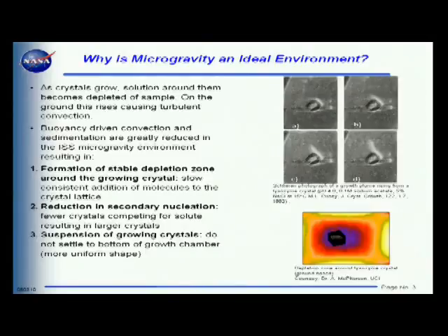What that in turn does is, instead of the crystal surface being exposed to a region of low concentration, which gives a diffusion limited growth rate, it is now subjected to the higher supersaturated concentrations, which will, one, cause rapid growth, and two, enable misoriented molecules to be trapped into the crystal lattice, thus giving you a lower quality structure.